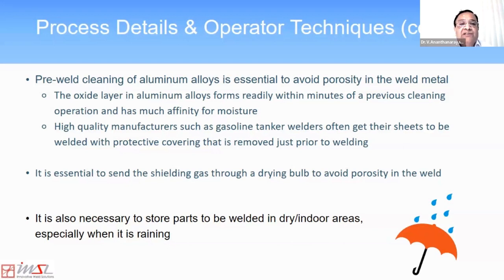And it's essential to also send the shielding gas for aluminum arc welding through a drying bulb to avoid porosity. If you have water content in your shielding gas, you are sure to get quite a bit of porosity in the weld. This was one of the problems I helped solve using the simple use of a drying bulb when they were trying to weld aluminum landing strips for aircraft for use in the Iraqi desert a couple of decades ago. And it's necessary to store the parts to be welded in dry indoor areas, especially when it's raining. I'm kind of repeating this since I know Mumbai has quite a few of these rainy areas.